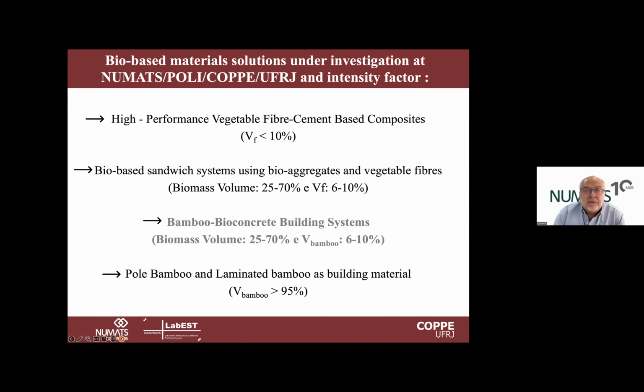So from the solutions that we are studying here, the first one, as I said, was the use of vegetable fibers. In this case, the volume of bio-based material is not that high. Normally, we use short fibers or textile. So typically, the volume fraction ranges from 2 to 10%, no more than that. This is the normal use we do. But recently, we started to use waste of agriculture, different kinds of waste from agriculture. So waste from wood production,